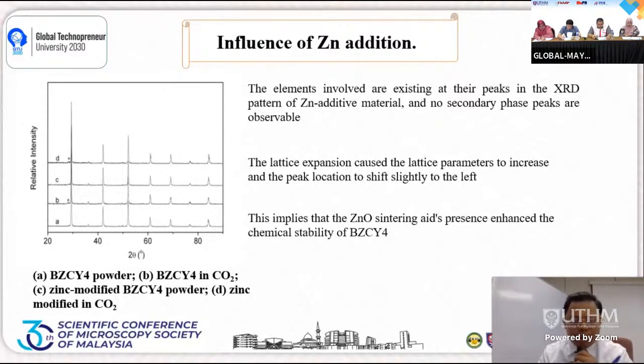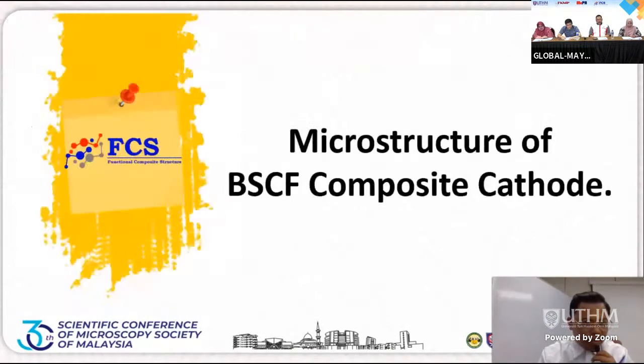Because the lattice expansion caused by the lattice parameter increase, the peak location is shifted slightly to the left. As you can see, on the left, the peak was highest at the first one, and this implies that zinc sintering present enhanced the chemical stability of BZCY4. And then we move on to the microstructure of BSCF.